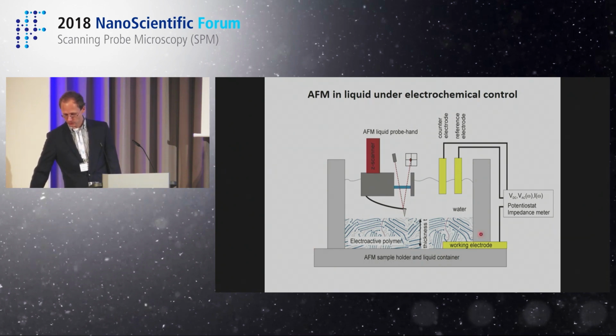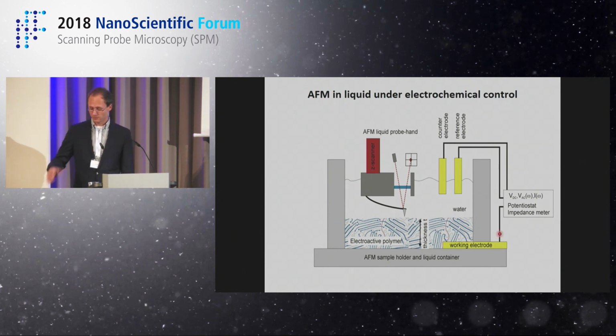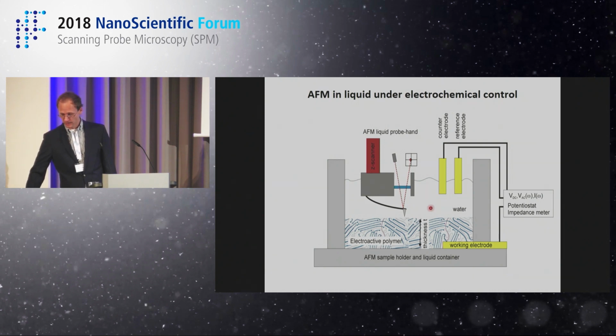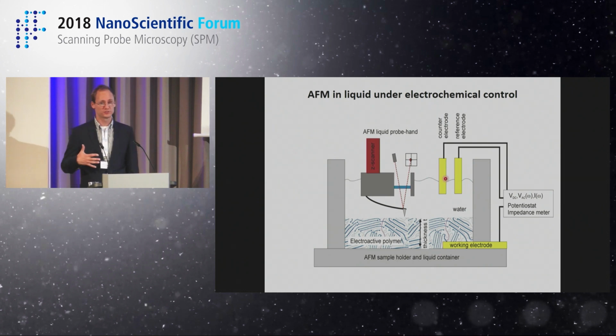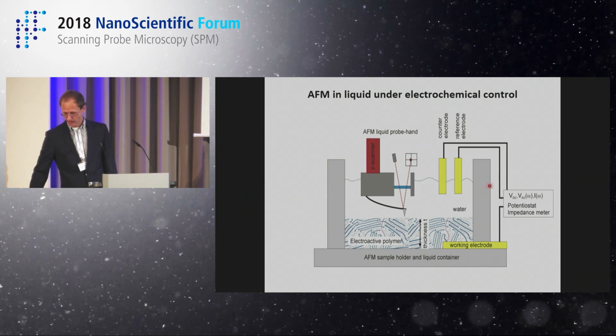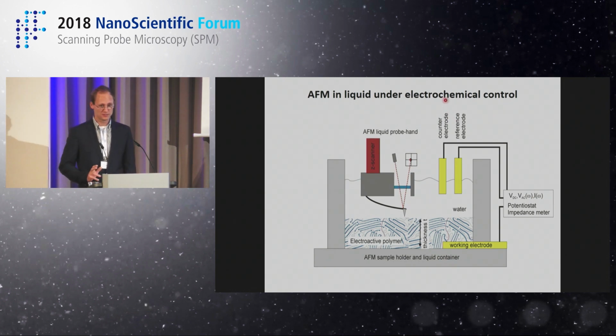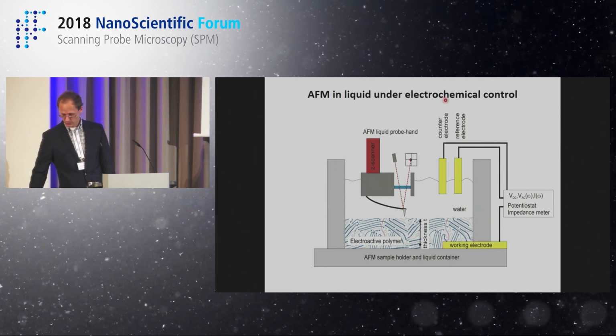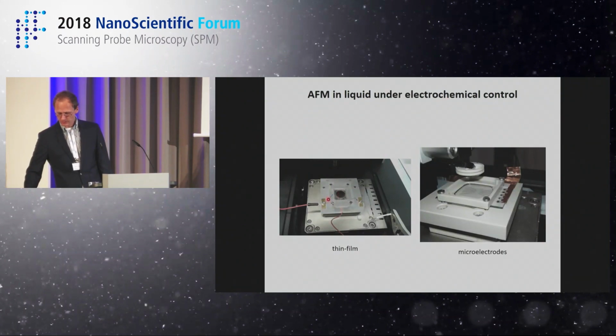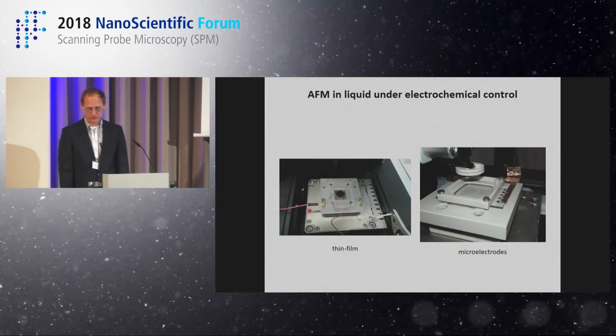But then you have to think, of course, also that here you have an electronic material. So you have to have the electronic contact. With electrochemistry, you have to seal these contacts with the external electronics, of course, nicely from the liquid that is inside here. And you need your typical electrochemical system in order to control potentials in liquid, which is the potentiostat. And of course, this one here, you have then to interface it with your AFM. It can be easily done with our setup, and it's working nicely. Here are some pictures of the measurement cells that we apply.